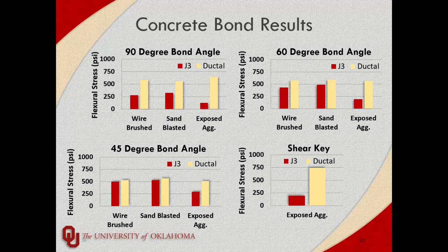All of the interface conditions showed that, except for the shear key, which we did the exposed aggregate on. All of the exposed aggregate conditions tend to be much, much lower for J3 than they were for Ductal. And they all failed at the interface.